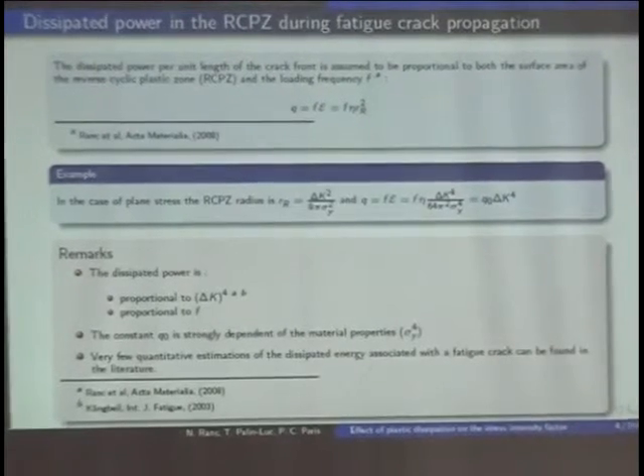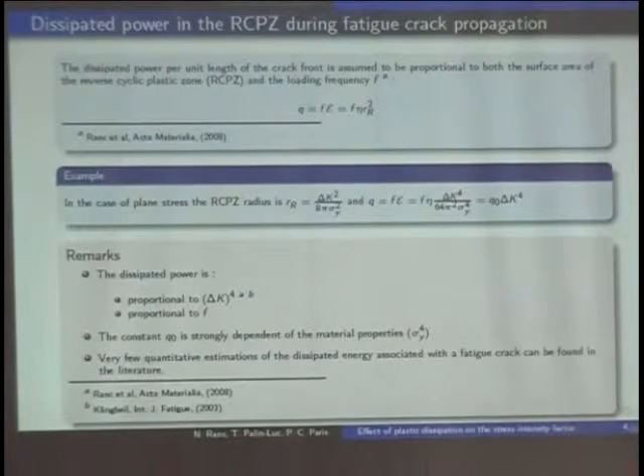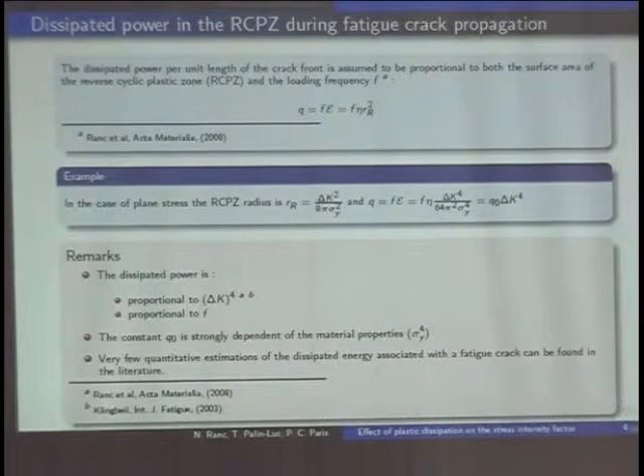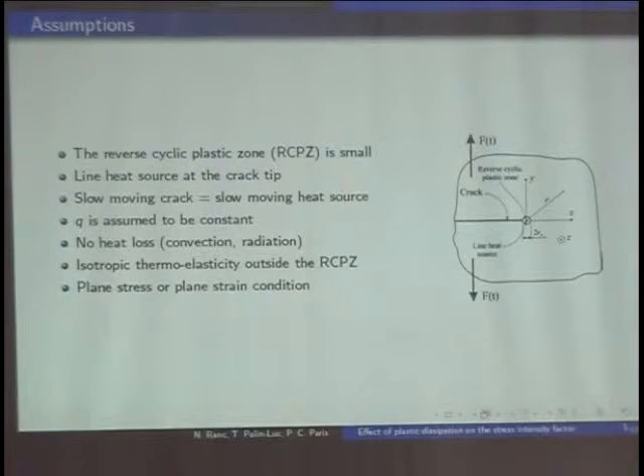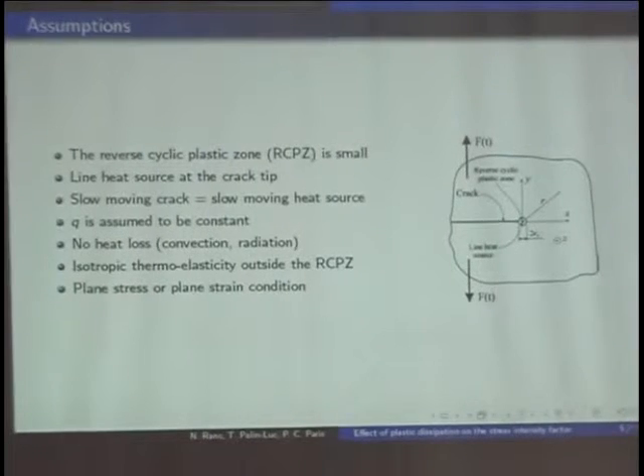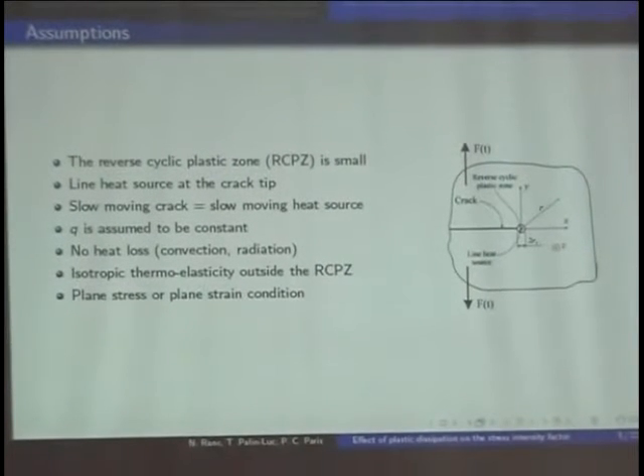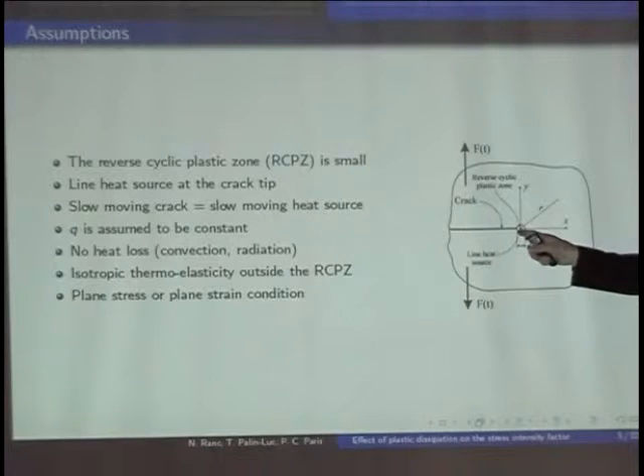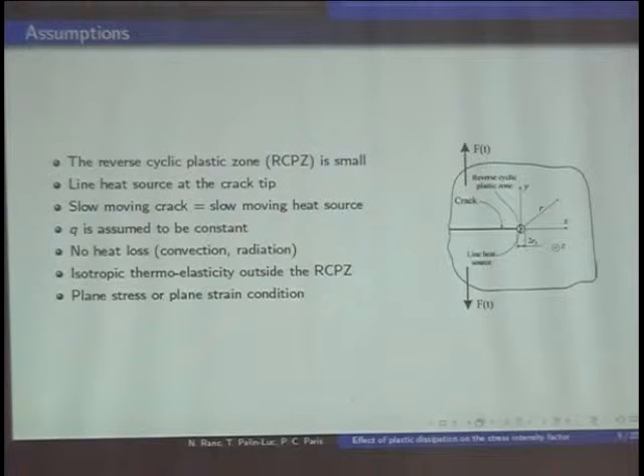Anyway, it's clear that there is dissipated energy, and now we will focus on how to estimate its effect on the stress field and on the stress intensity factor. The assumption of the presentation, to be able to solve the problem analytically, is the following. We consider that the reverse cyclic plastic zone is small compared to the size of the specimen, and in this case the reverse cyclic plastic zone can be modeled by a line heat source, a local heat source. In this case, an analytical solution exists. We will see it's not very difficult.